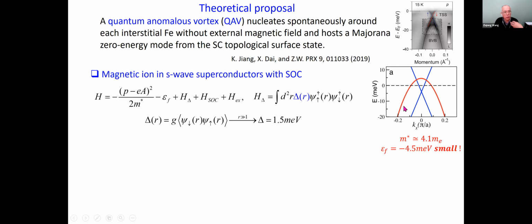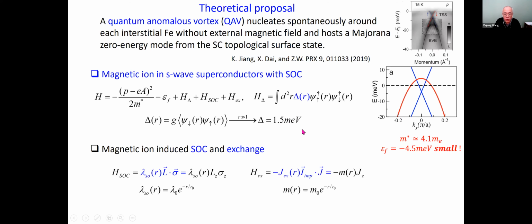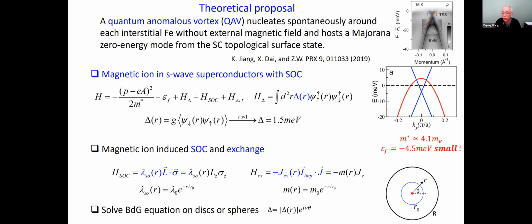So I can sketch the philosophy. The red line is the whole band around the gamma point, the bulk band. The blue one is the surface state. To get QAV, the quantum anomalous vortex, we work with the bulk bands, not the superconducting topological surface state. And we took parameters from ARPES. And of course, the magnetic ion is put there with an exchange coupling to the total angular momentum of the quasi-particle. And we do the whole thing on a disk by solving the BdG equation in the presence of a vortex.